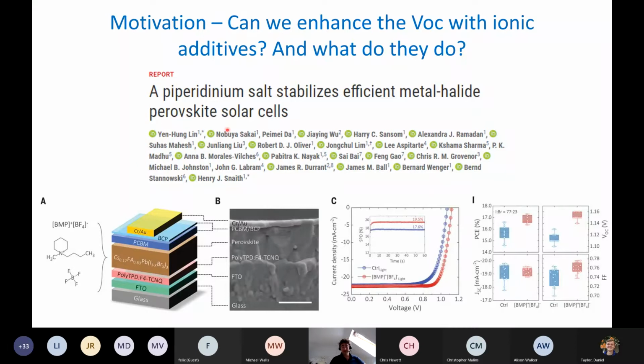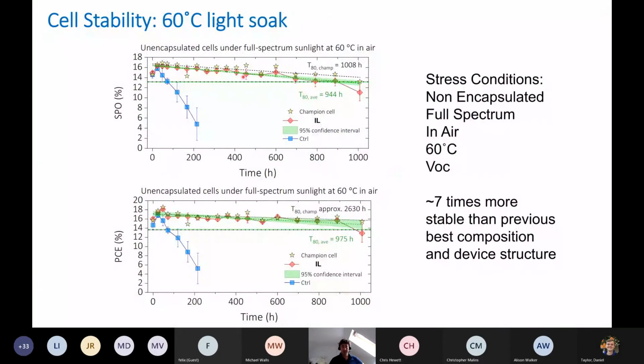One thing we discovered a year or so ago was that we could add certain ionic salts. There's additives we can put into this perovskite material, and they can have a positive impact. This is an example of a piperidinium salt that when put into this composition of perovskite gives an increase in voltage. Very importantly, it gives quite a significant increase in long-term stability.